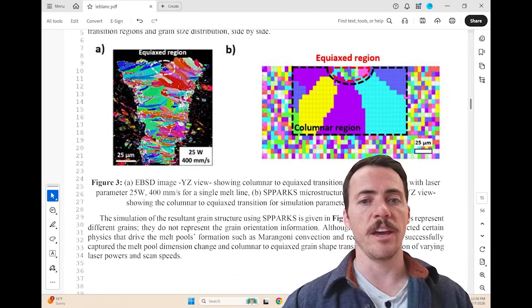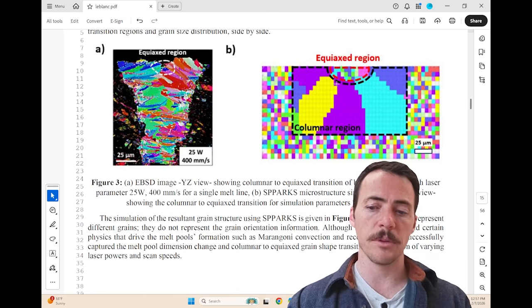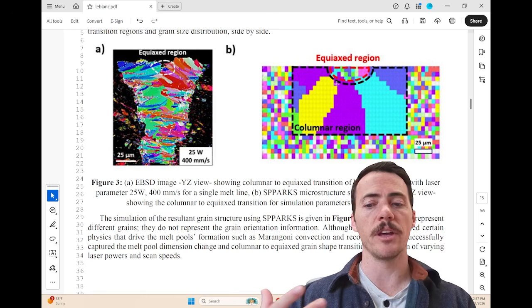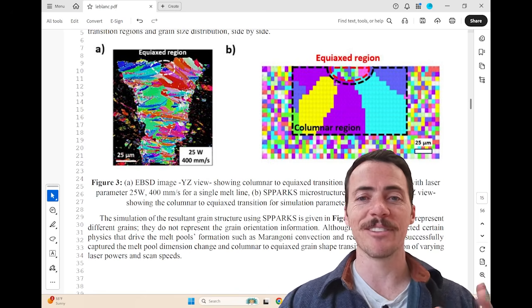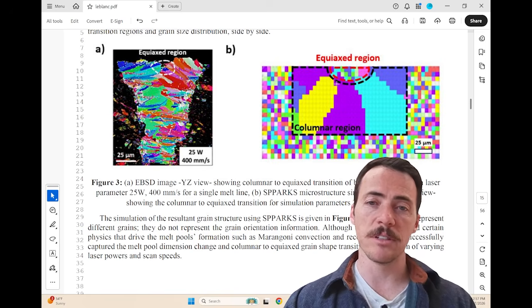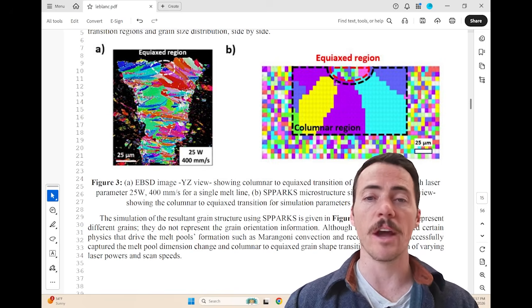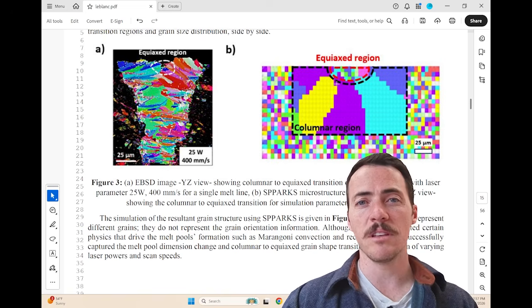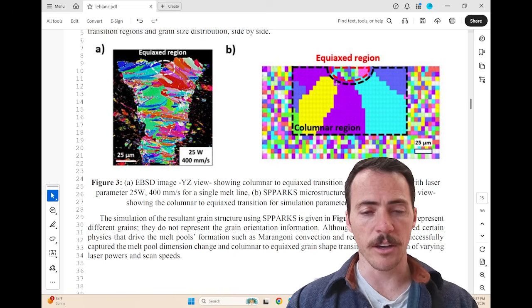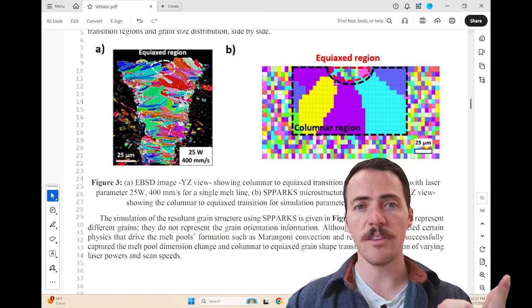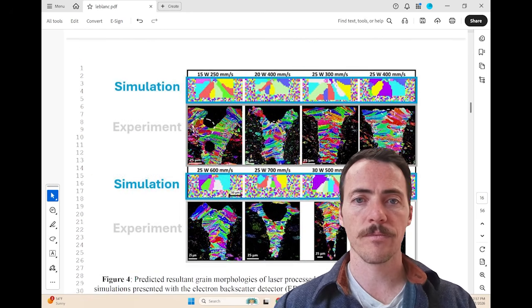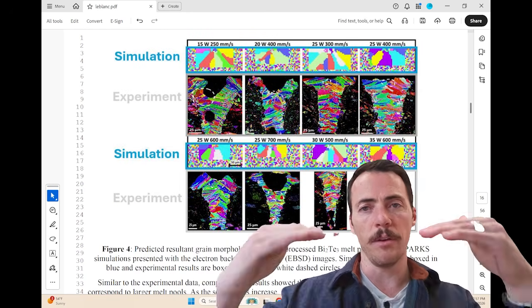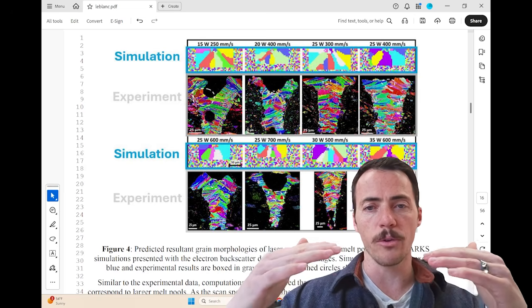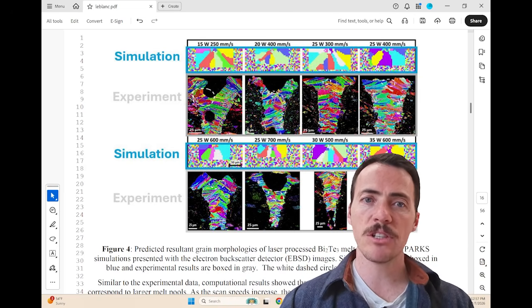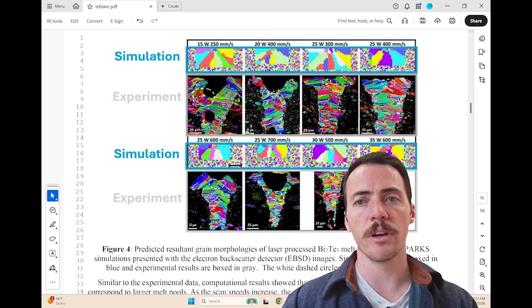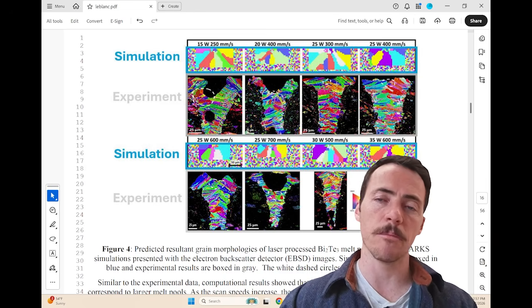What we're doing here is a finite element method to capture the thermal simulations. And then they're pairing that thermal simulation with the Sparks code, great name, right, out of Sandia National Lab. And that's going to allow them to simulate the microstructure that arises from this. Ultimately, what they're able to see is pretty good agreement in the grain morphology, the grain size, and the spatial distribution. You can see how well the above sections boxed in blue versus the lower sections in gray for each of these different conditions matches pretty well what they were able to try and simulate with this simulation package approach.